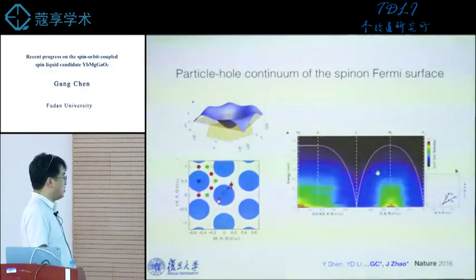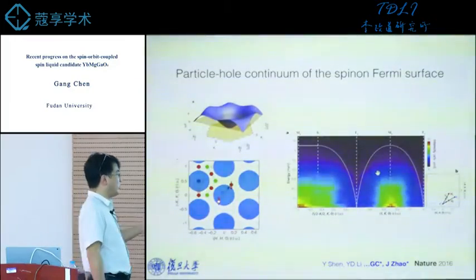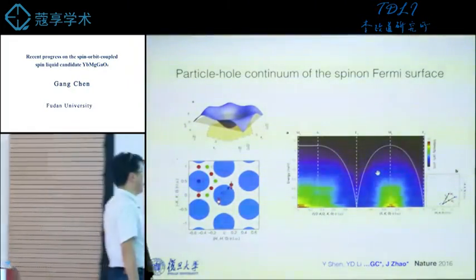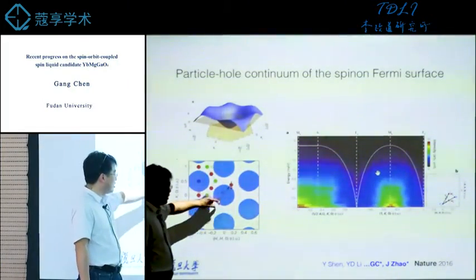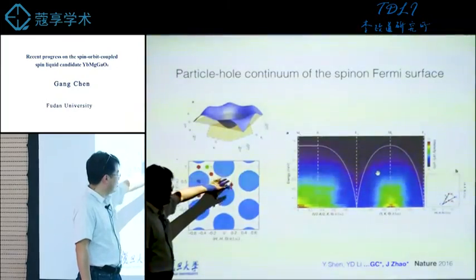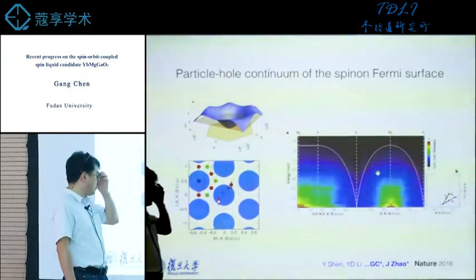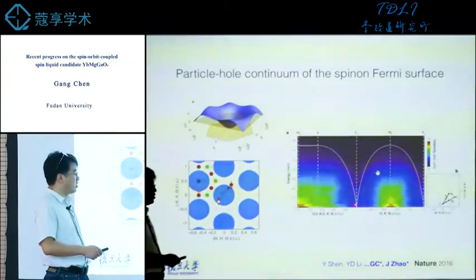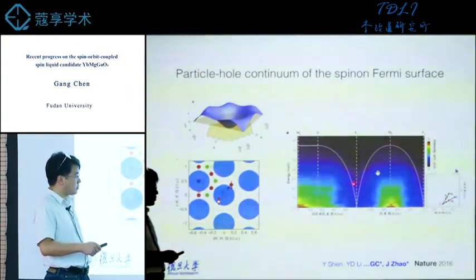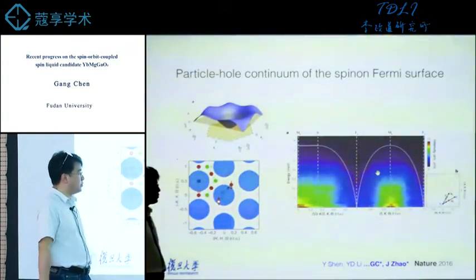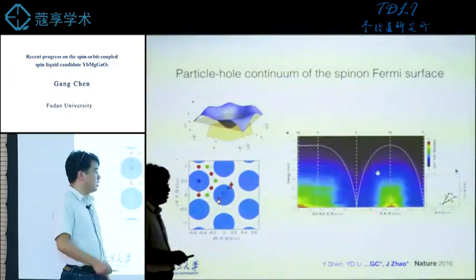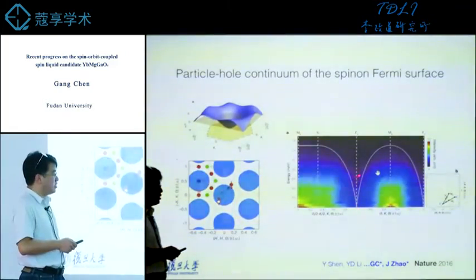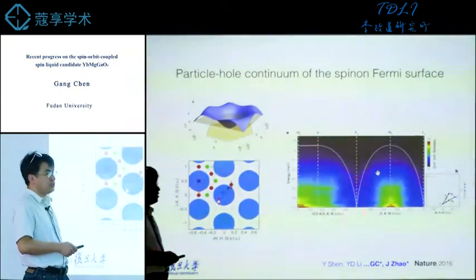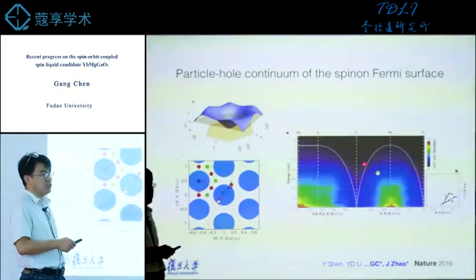So this neutron scattering measures the particle excitation across the Fermi surface. So this particle excitation can be here, or here, or here. So that explains why there is a broad continuum at low energies. Moreover, if you increase the energy, near the gamma point, there is the suppression of spectral intensity.